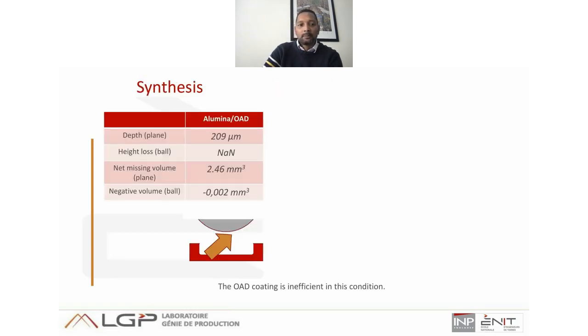So we can present this and use all this information from the topographic analysis to build a tribological circuit like the one proposed by Berthier. In the first case with OAD, we see that there is a lot of production of debris from the coating and also from the alumina substrate.